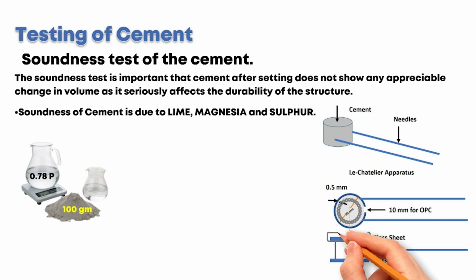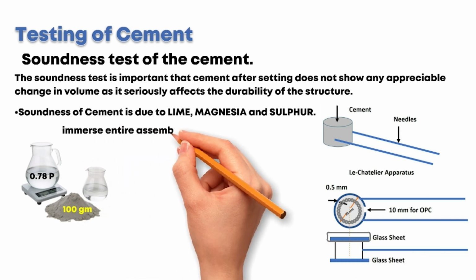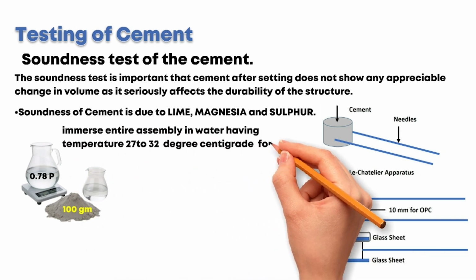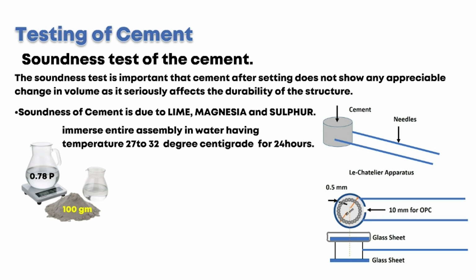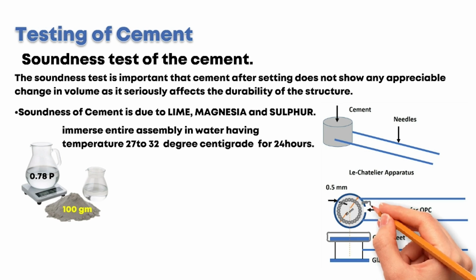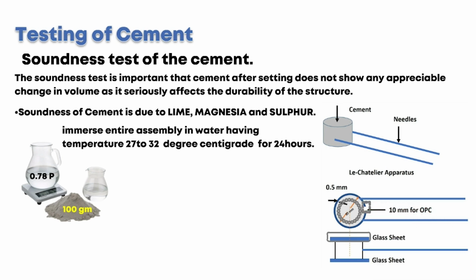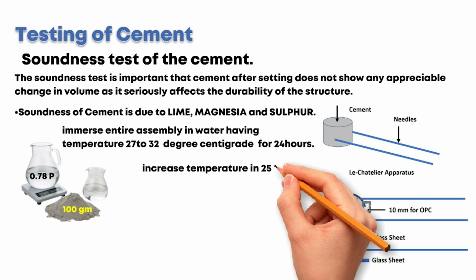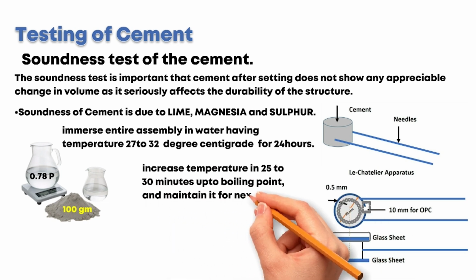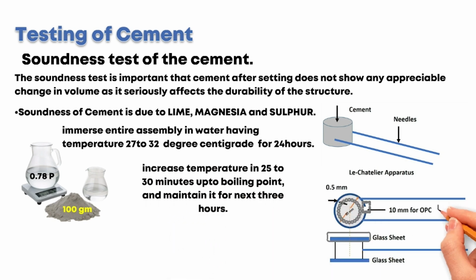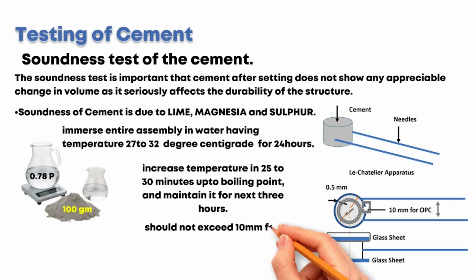Cover top and bottom with glass plates and immerse the entire assembly in water, having temperature 27 to 32 degrees centigrade for 24 hours. Remove the mold and note the displacement of the split with the help of indicator arms. Then again, immerse the entire assembly, increase the temperature in 25 to 30 minutes up to boiling point, and maintain it for the next 3 hours. Note the displacement of the split with the help of indicator arms. The difference in reading in both parts of the test should not exceed 10 mm for ordinary Portland cement.